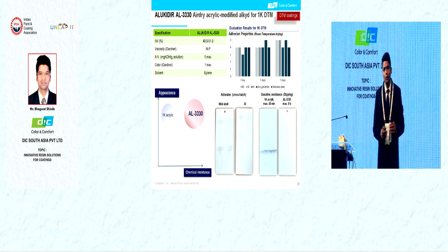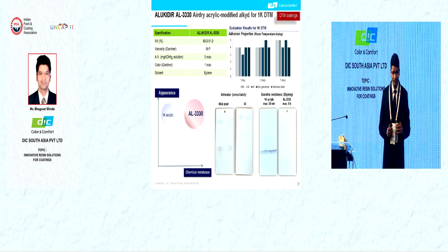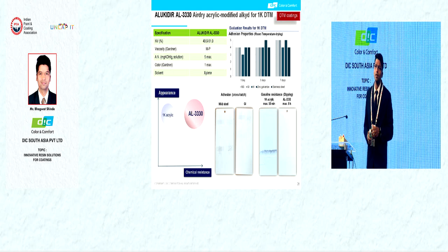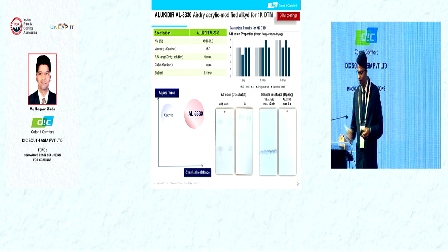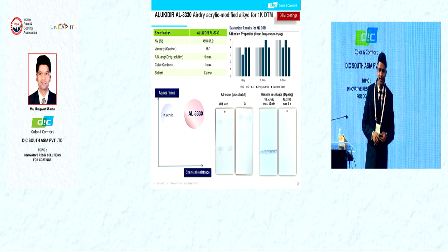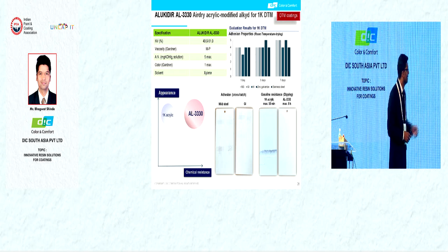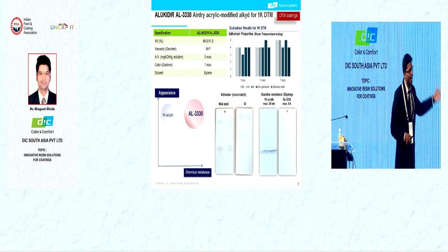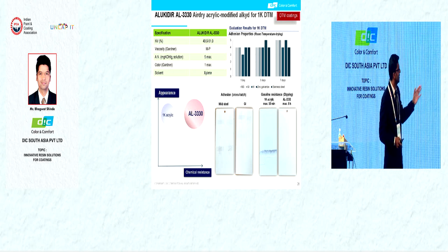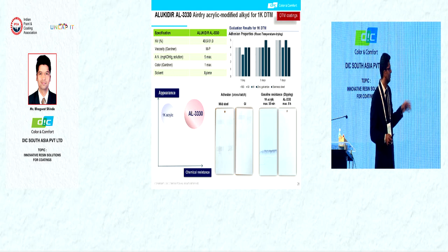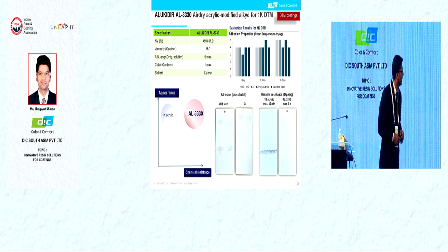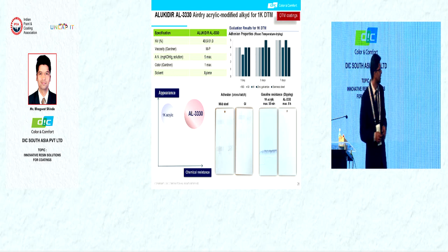The next one is Alukidir AL-3330. This is acrylic modified alkyd. This product has the specialty of very good solvent resistance as well as chemical resistance. You can see here the gasoline resistance of that product. This is the 1K acrylic product, and here is AL3330. After 6 hours, there is no defect or any change of the film after the gasoline resistance. And this product shows a good adhesion to GI as well as mild steel.